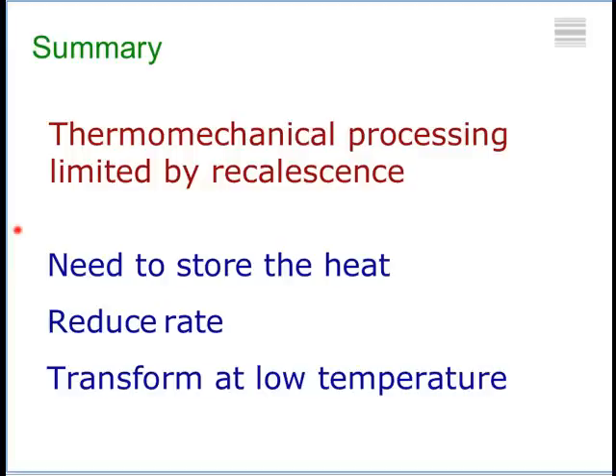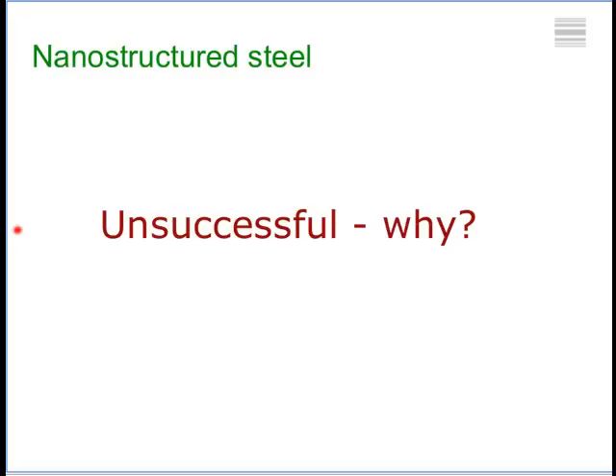Now, just like carbon nanotubes, there's a huge amount of research which has been done to produce nanocrystalline steel. And most of that research has not been successful. Okay? So millions and millions of pounds have been spent to produce nanostructured steel, and it hasn't been successful. The aim, of course, is to produce a good combination of strength and toughness. Now, the reason why it hasn't been successful is that as you make your grain size smaller and smaller, you're introducing more boundaries inside your material. Those boundaries have a lower density than the rest of the crystal. So defects like dislocations sink inside the boundaries. So you're left with regions which are completely free from dislocation.